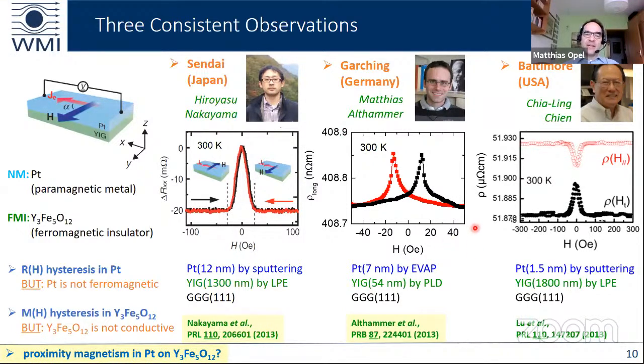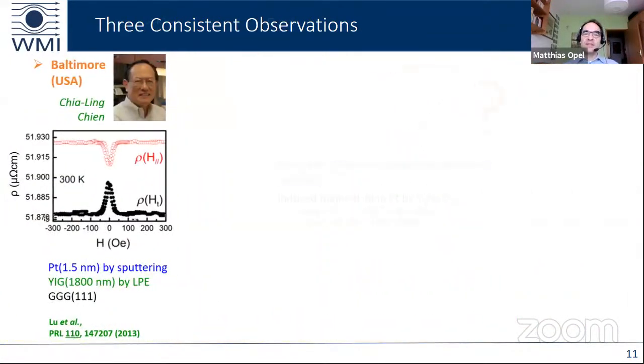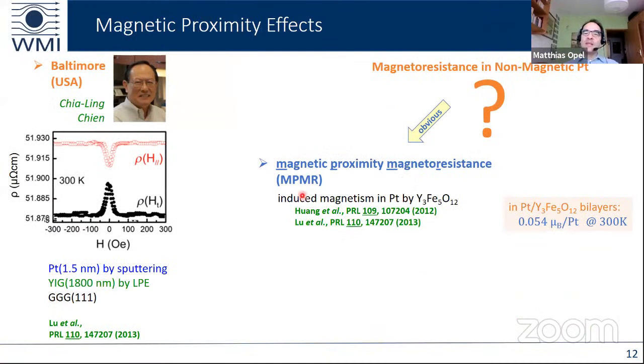One of the first explanations would be that platinum just becomes magnetic or ferromagnetic on the ferromagnetic YIG due to a proximity effect. This is known as the magnetic proximity magnetoresistance. Indeed, the Baltimore group found via element-specific magnetization measurements that their platinum shows a magnetic moment of 0.054 Bohr magnetons per platinum atom at room temperature.